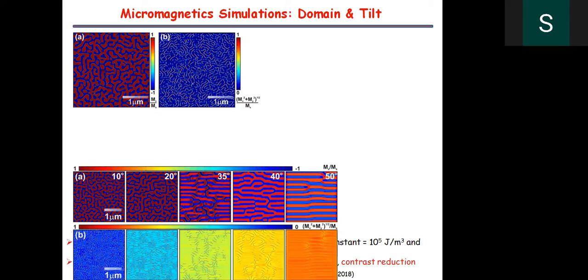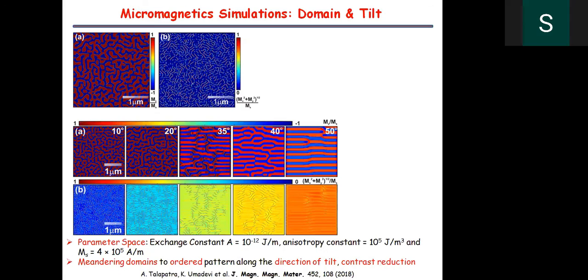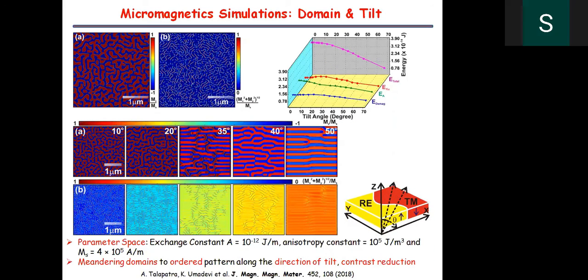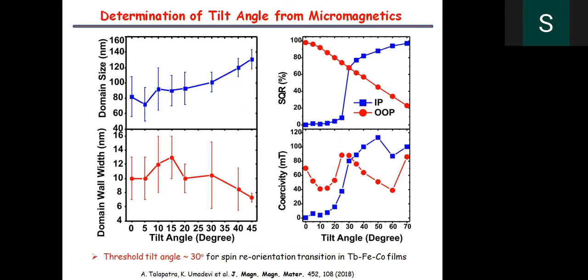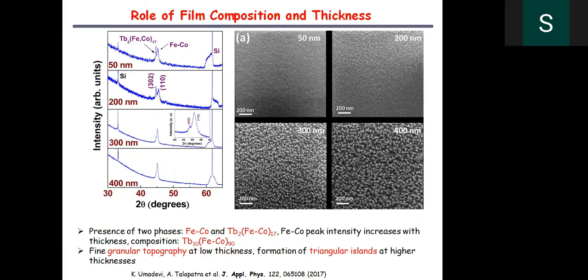We have also done a variety of magnetic simulations to find the tilting magnetic anisotropy by using OOMMF, the object-oriented micromagnetic framework, and we could find what tilt angles are present in these materials by using detailed micromagnetic simulations. We found the contributions from different energies, anisotropy energy, demagnetizing energy, Zeeman energy, and we tried to correlate with the experimental findings. We also tried to understand the role of thickness and composition at some other composition.